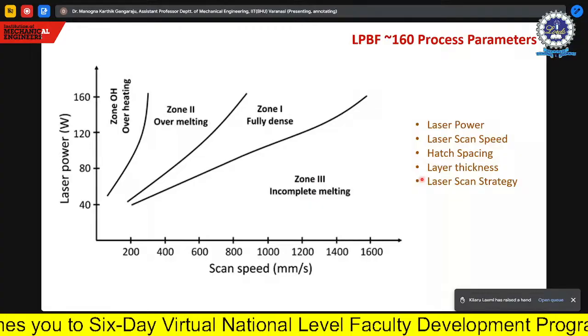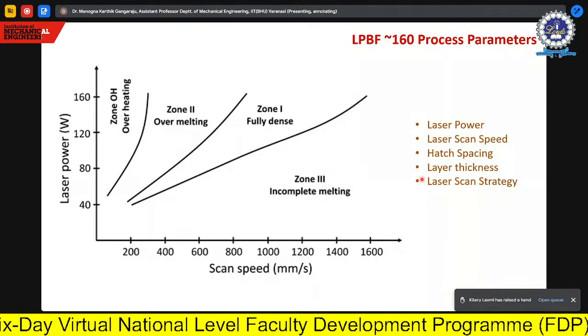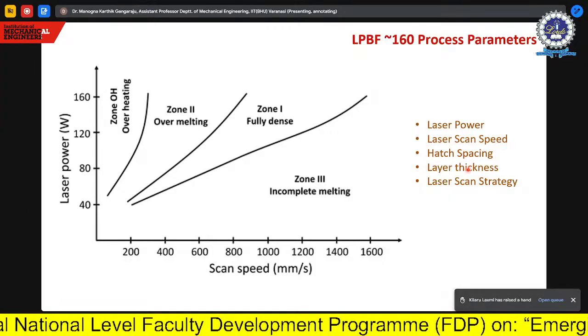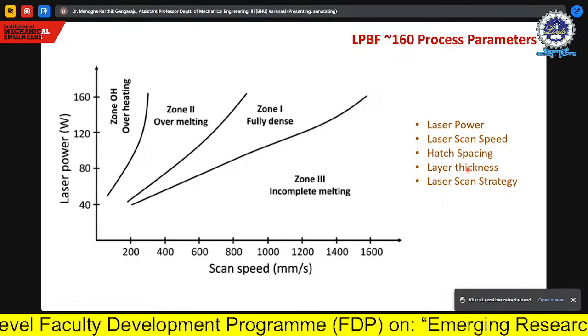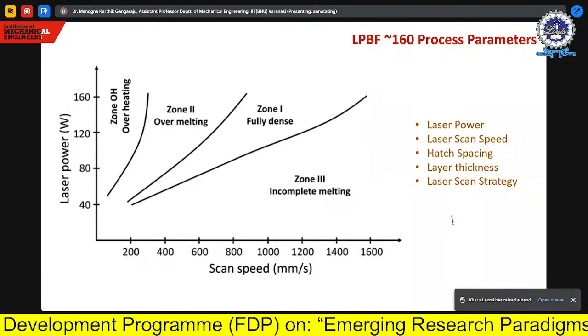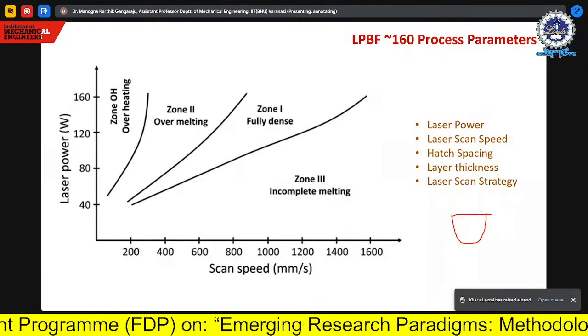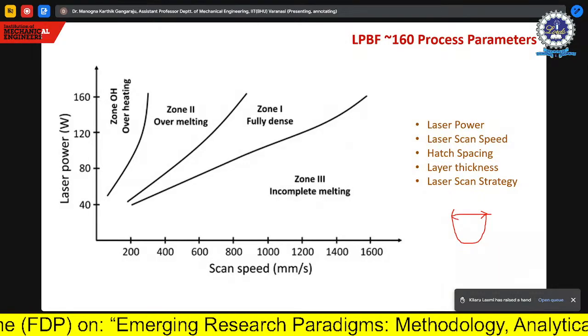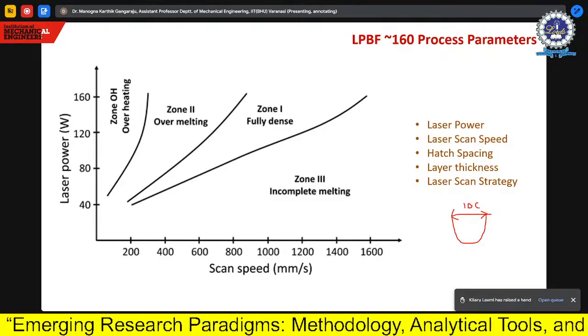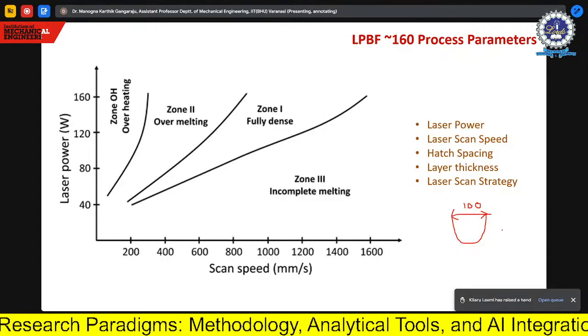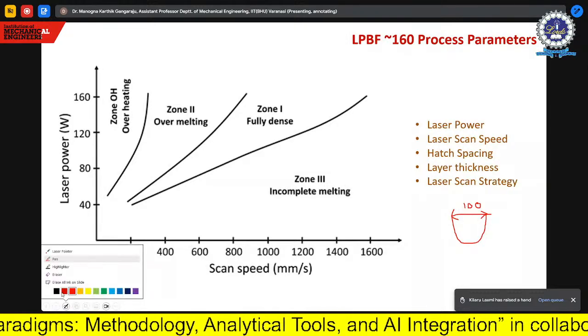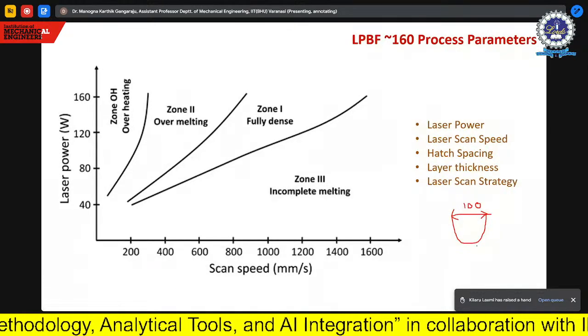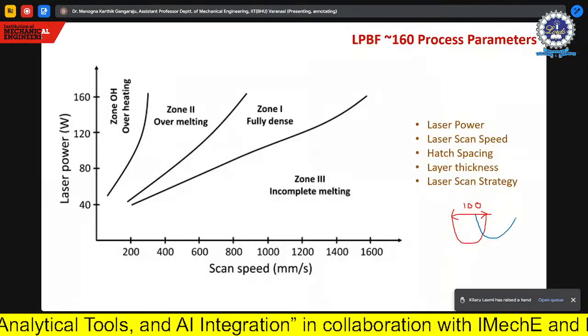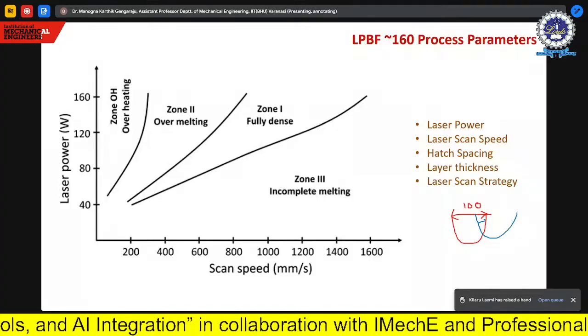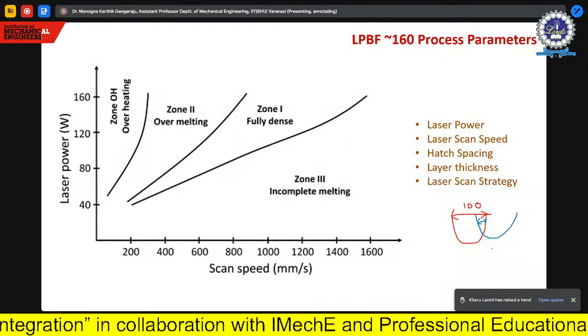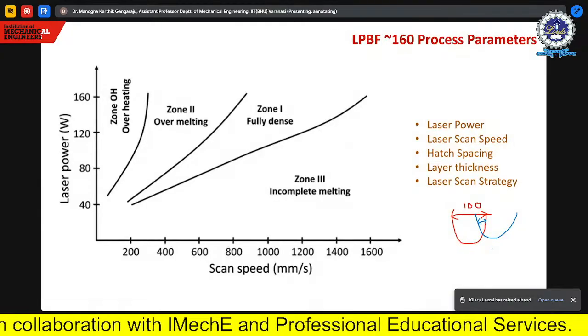Generally they keep hatch spacing of a particular value. You generally maintain 30% of overlap. So let us assume the size of your track is 100 microns. So this is your 100 microns track that you are able to achieve for a given power and scan strategy. Generally, you maintain 30% overlap, so your overlap distance is generally 30%. Okay, so this is a general rule for hatch spacing. It's not always the correct value, but it is a general recommendation.